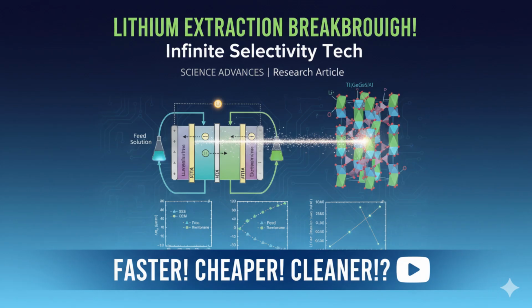Second, and this is crucial for this application, this specific type of Nasicon is remarkably stable in water. Many solid-state electrolytes just fall apart or react when you put them in contact with aqueous solutions. Right. That wouldn't work very well then. Not at all. So finding one that's stable is a big deal. But the real magic, the secret to that incredible selectivity, is the mechanism. It's what they call anhydrous hopping. Anhydrous hopping. Okay, break that down. Anhydrous meaning without water. Exactly.